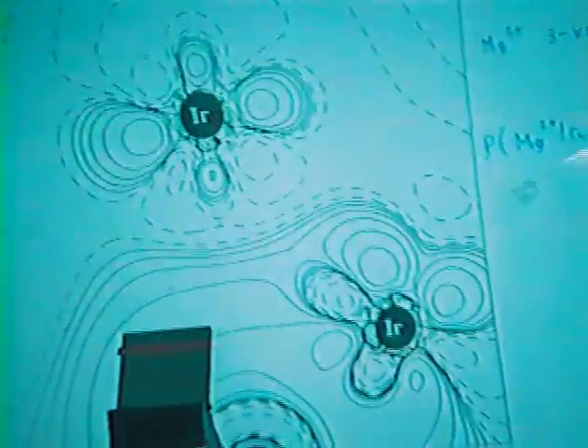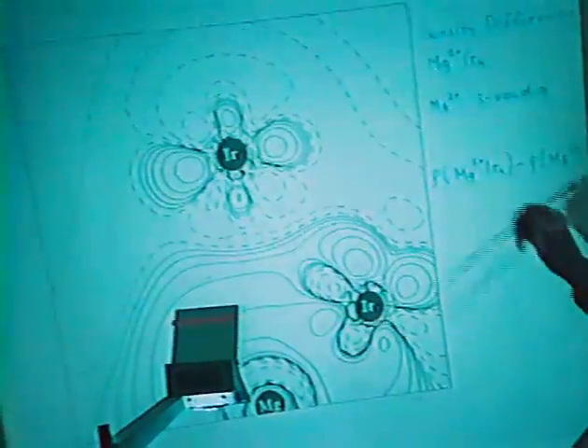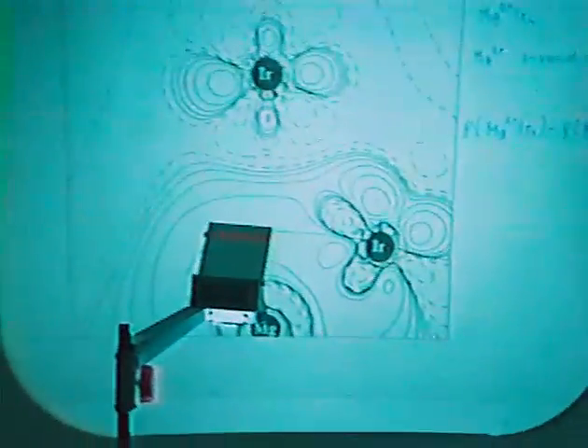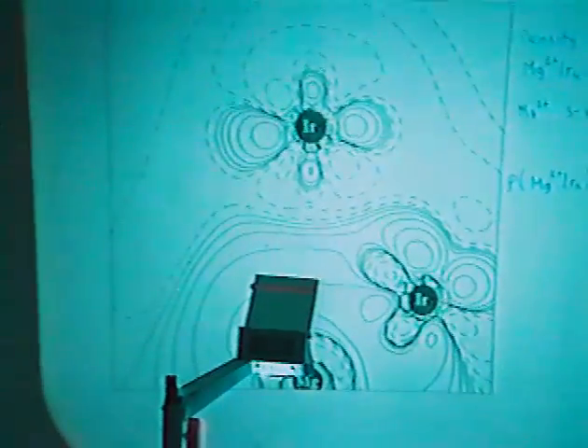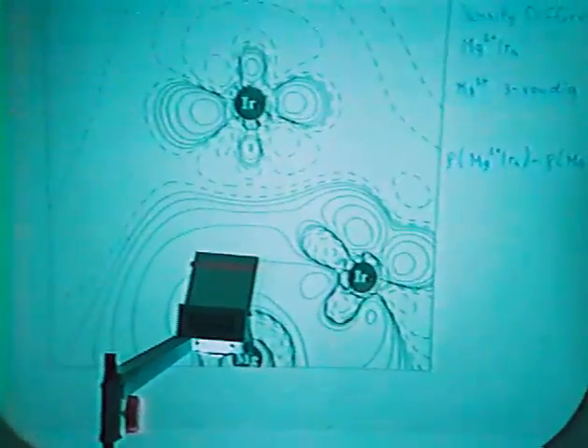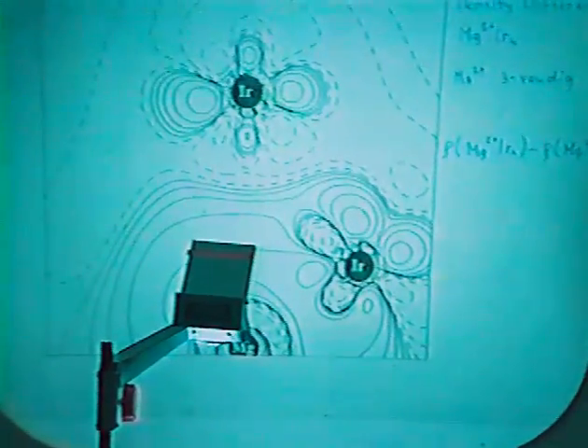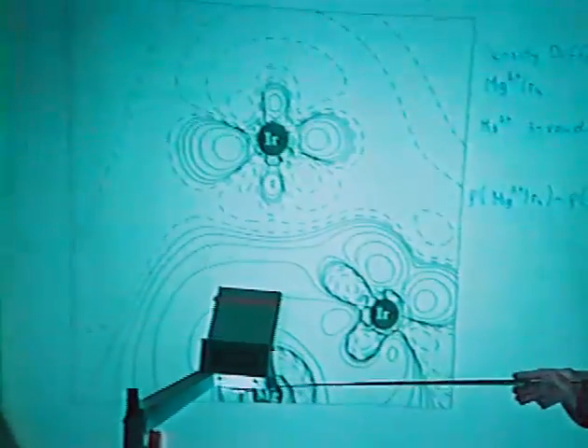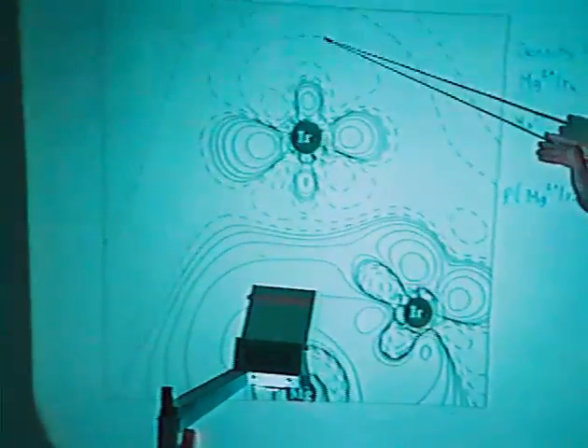But you see it more clearly in the effect of the cation on the cluster. You will calculate a so-called density difference plot. What you do is you subtract from the final electron density that of the isolated atoms. And then you get something like this. With the dashed lines, we depict a decrease in electron density, and with the solid lines, an increase in electron density. So in the presence of the cation, we cause a decrease of electron density on the top of the cluster.